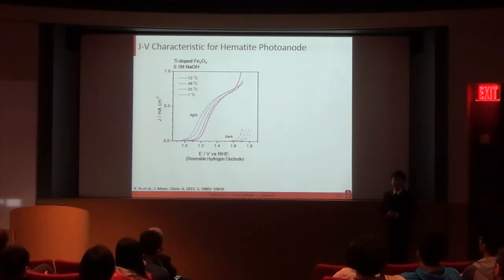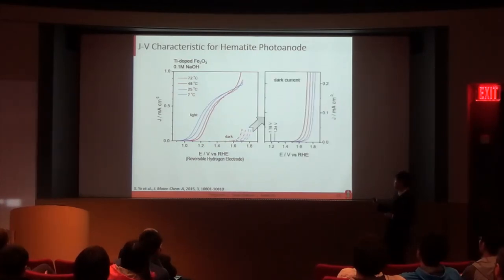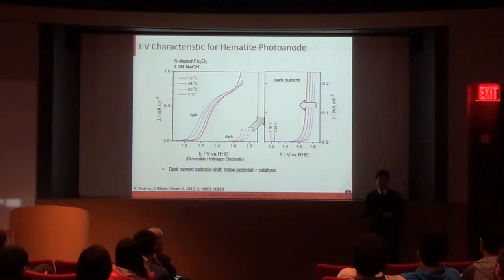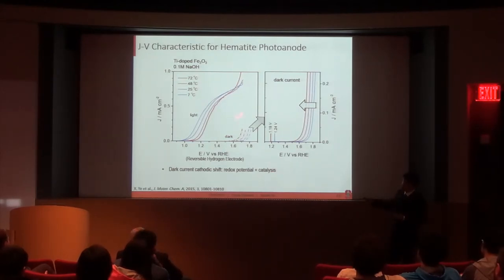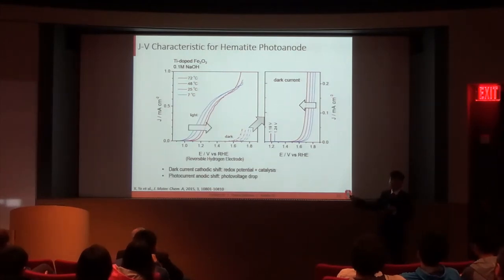So here is the temperature-dependent JV characteristic for the hematite photoanode. Let's look at the dark current first. The dark current shifts in the cathodic direction, which is the same direction as the redox potential shift. While the dark current shifts by a larger amount than the redox potential shift, this is because there's a convoluted effect of the thermally enhanced catalysis. Looking at the photocurrent, it shifts anodically. This is expected because the photo voltage drops with increasing temperature, as we discussed.